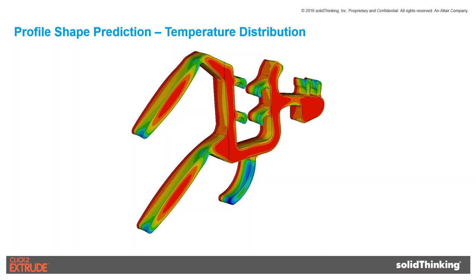Here we can see the polymer flowing through the die and coming out of the die. Because of the viscous heating, the temperature will rise. Here we can see how much the temperature rises in the die as the material is flowing through. This will help us understand if the temperature rise is within the limit, or if it is uniform across the die exit. If there is high variation in temperature, like what we are seeing here, where the bottom rib is coming out a little bit colder, we will see some defects because of variations in the temperature.